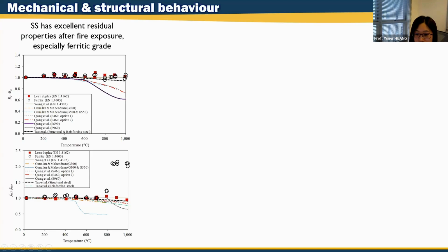So you can see the red dot is lean duplex, the black dot is ferritic. Both ferritic and lean duplex stainless steel, after being exposed to 1000 degrees Celsius, show no change of Young's modulus. And for the strength, lean duplex stainless steel does not reduce, but the ferritic stainless steel after exposure actually goes up. It does not reduce, it actually goes up by more than double of the original strength. So this is quite impressive. You can see the other carbon steel materials, S460, S690, G300, they all reduced, the properties all reduced after exposure to high temperature.